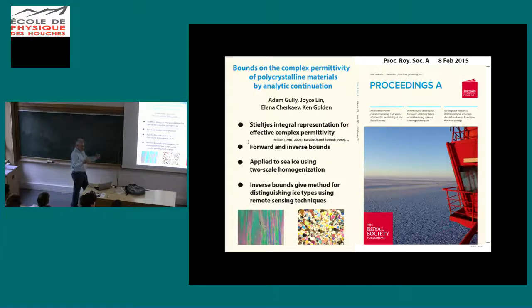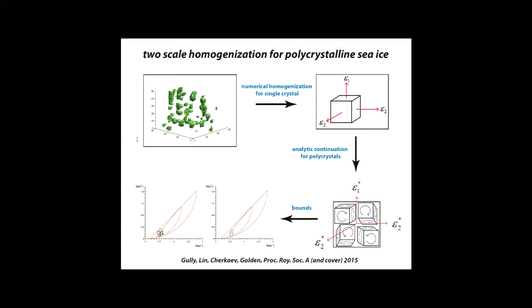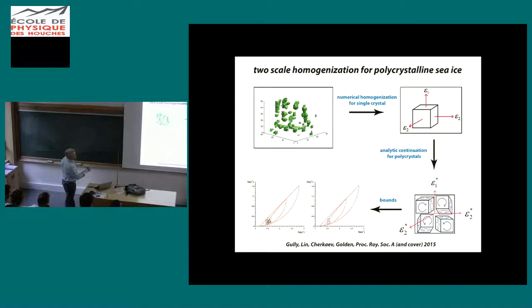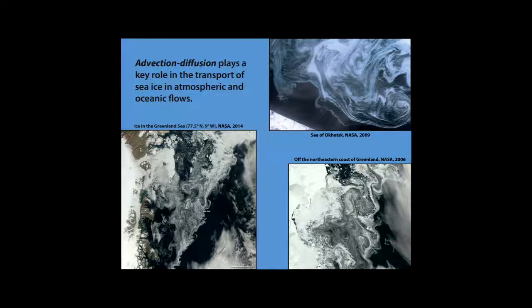So we're really interested in being able to electromagnetically distinguish between these two ice types. It really affects the biology a lot. Ecologists are really interested in this distinction, particularly Antarctic people. The two-scale homogenization process, here's an individual crystal. We numerically figure out the effective complex permittivity tensor for one individual crystal, and then we have information about the statistics, and then we analytically derive these very tight bounds on the complex permittivity, given information about the orientation statistics.